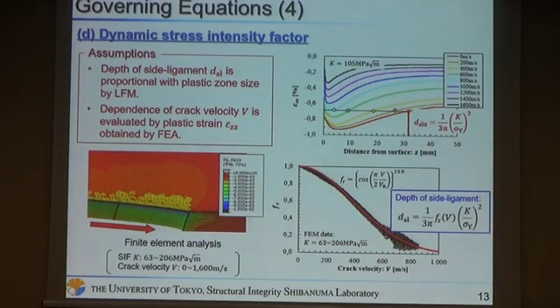In the calculation of the area of the side ligaments, we employ two assumptions. First, the depth of the side ligament is proportional to the plastic zone size by linear fracture mechanics theory. And second, the dependence of crack velocity is divided by plastic strain obtained by finite element analysis. Consequently, the depth of the side ligament is formulated in this form.